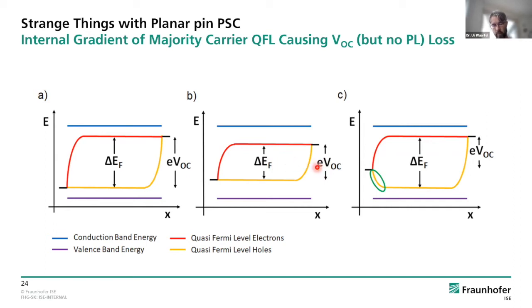Now, again, we have seen a more or less high PL intensity, but a low VOC at the same time. And there's only one possibility how this can happen. And this is depicted in this picture. In this picture, we assume that at the hole contact, it could also be at the electron contact, there is not only this gradient of the minority carrier quasi-Fermi level, of the electrons, but also of the holes. Okay, this can happen.